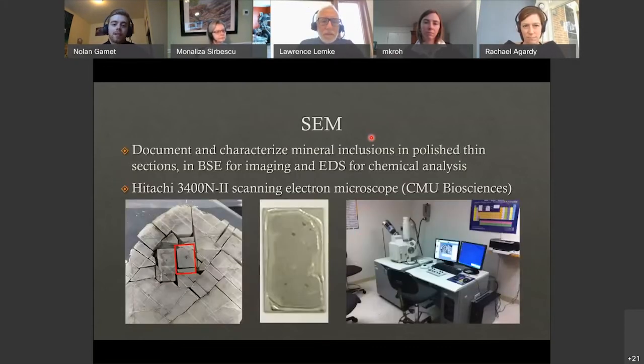For scanning electron microscopy, we use this to document and characterize the mineral inclusions in the polished thin section chosen from TM17. Backscatter electrons were used for the high resolution imaging, and energy dispersive spectra were used for chemical analysis to make the 2D maps. And then we used the Hitachi 3400N2 scanning electron microscope located in the CMU Biosciences building.